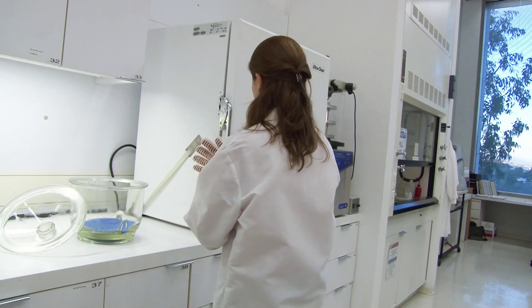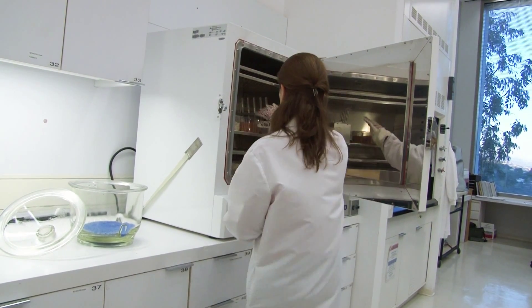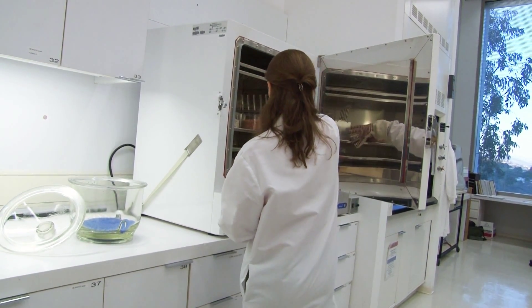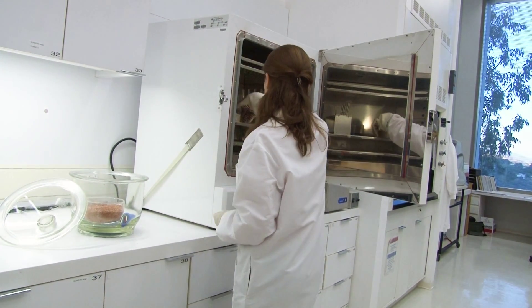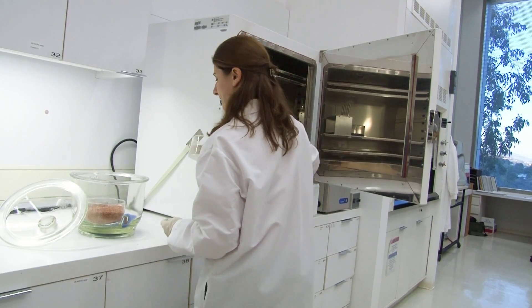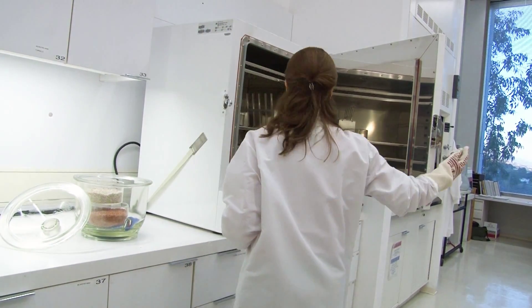Repeat the drying and weighing procedure until a constant weight is reached. This is achieved when the difference between two successive measurements at a 24 hour interval is less than or equal to 0.1%.